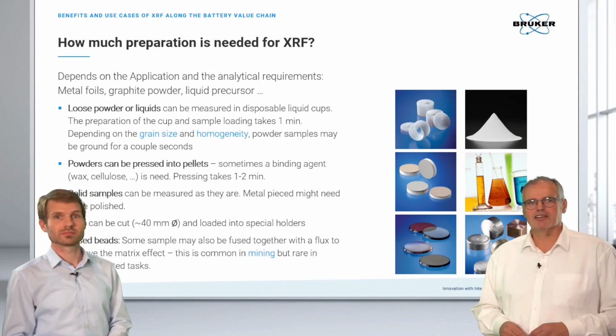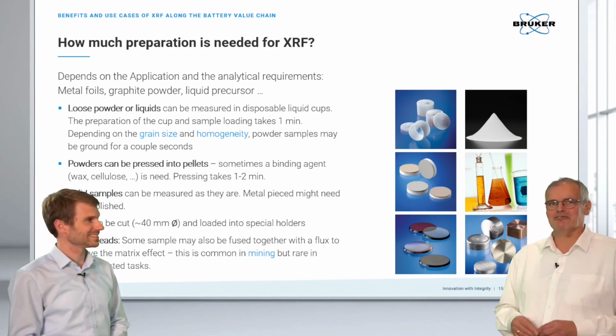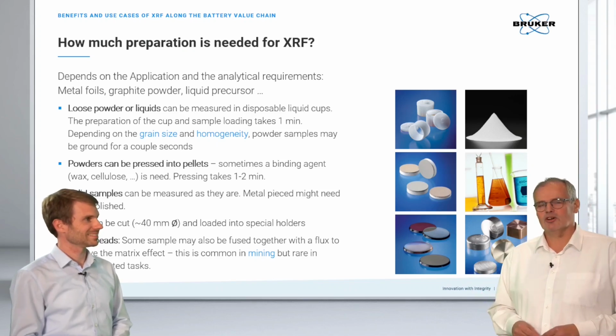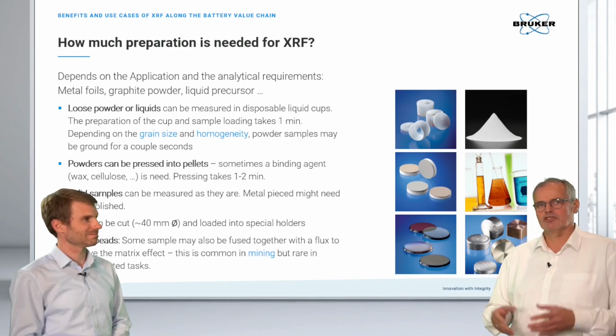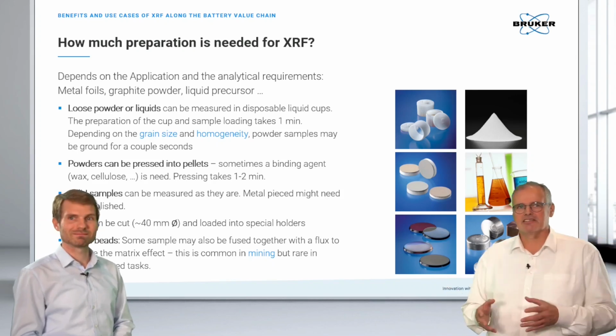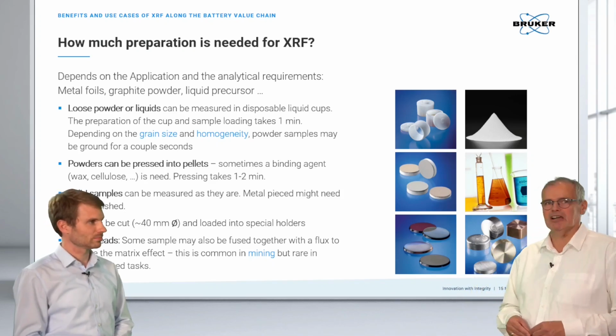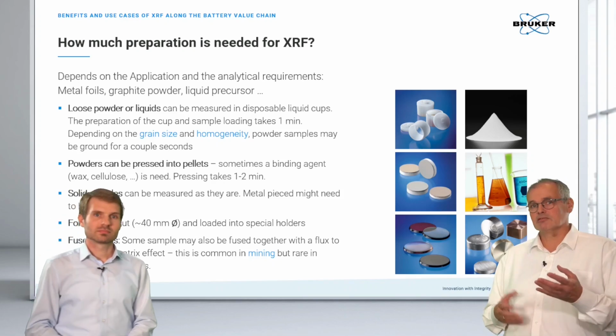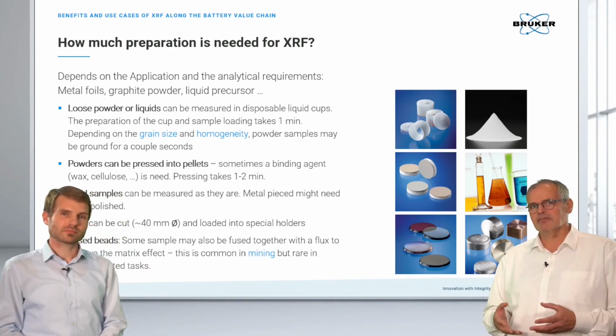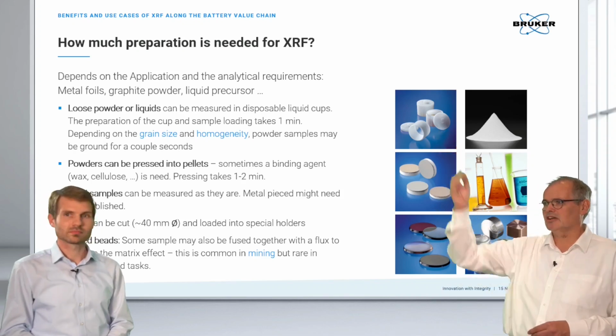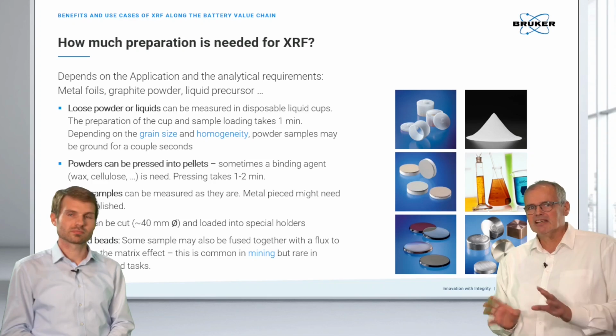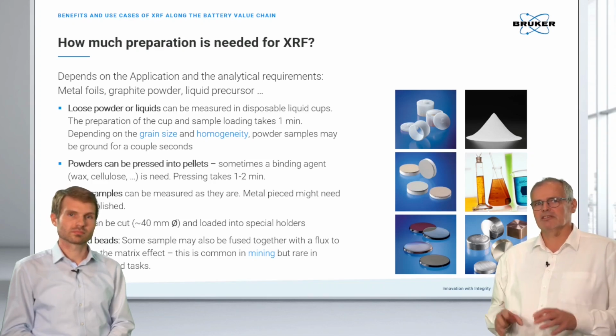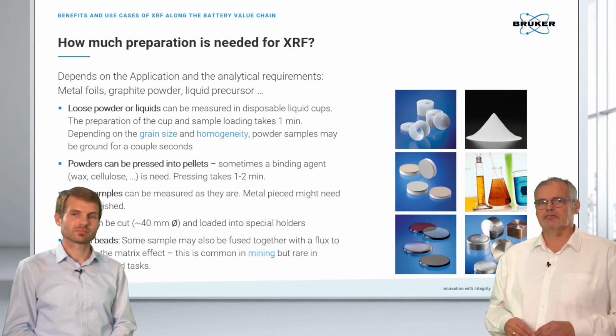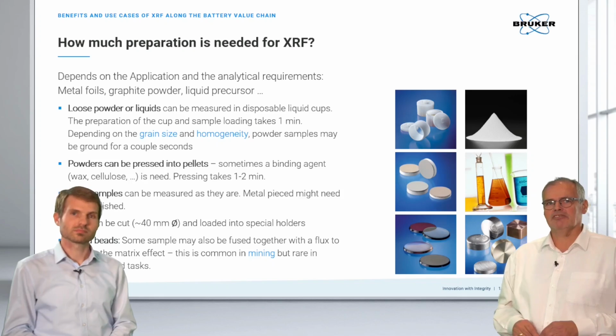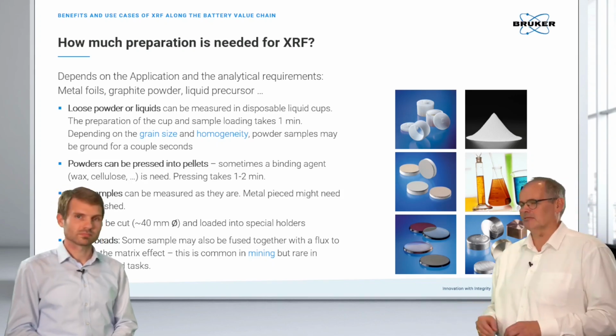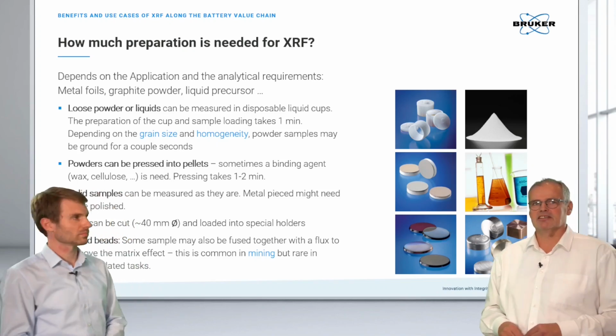Now I want to solve the riddle from the beginning. The big advantage of XRF, I said, is that we are using an effect in the atom shell which uses inner shell electrons. And therefore, we are independent with XRF of the chemical binding and also the state. So we can analyze loose powders or liquids. These can be filled into liquid cups, which are shown here, and analyzed directly. There are some pros and cons. The one thing is the grain size can have an influence. Also, homogeneity might be a factor, but nevertheless, that's a very quick, easy way. You fill the powder or liquid in and analyze it in the instrument.